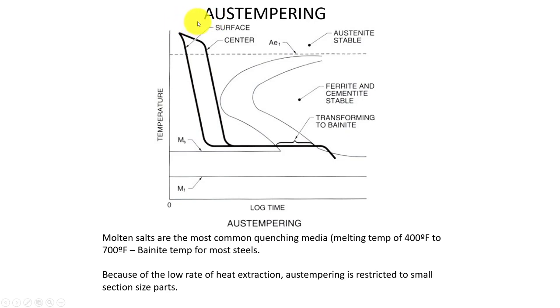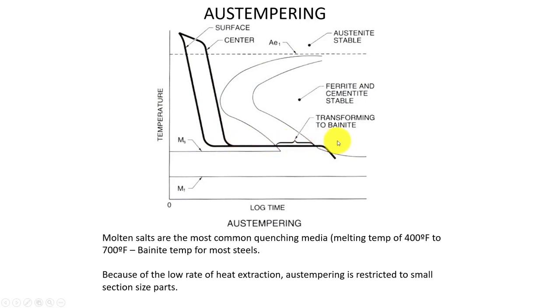How would I make bainite? We call this a process called austempering. Normally when we make martensite, we have to go and temper it, so austempering is where we make bainite instead. If I have liquid salt at these temperatures, I can drop my piece of metal in — this is for smaller pieces of metal, like 1040 steel or 4140, fairly smaller cross sections. I'm not going to see a huge delta T in the quenching, putting less stress and possibly avoiding quench cracking. Since it went into salt, it's going to hit this temperature, didn't get to the martensite start, and it's going to shoot through the bainitic areas — we're going to end up with bainite. What does bainite look like under a microscope? It's dark and feathery compared to white and feathery for martensite. It's a nice process because it's not as hard and you don't have to temper it — that's why it's called austempering.